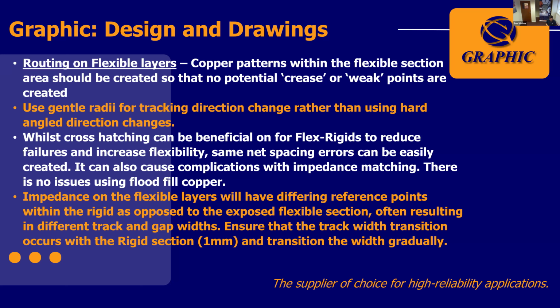When it comes to impedance matching across a flex rigid, what you will typically find is that it's not always the case that there are differing results. But when you're running a 50 ohm single-ended or say a 100 ohm differential pair from the rigid section on the flexible layers, from the rigid section across the flex, perhaps into other rigid sections, because you have differing reference layers, you may end up having different track widths required in the flexible section as opposed to the rigid, because in the flexible section, you might just have the coverlay and air as your reference because you've obviously depth milled and removed all the rigid material out.